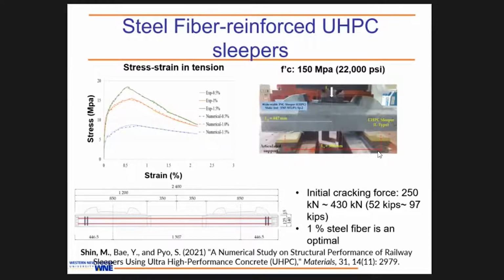When you conduct a direct tension test with the dog bone shape of concrete with fibers, the fibers are well aligned or well distributed. It's not so random. But when you use that dog bone stress strain curve in a real structure, the orientation of the fibers is not well distributed. So there is a fiber reduction factor, and what we found is that it is about 0.85.